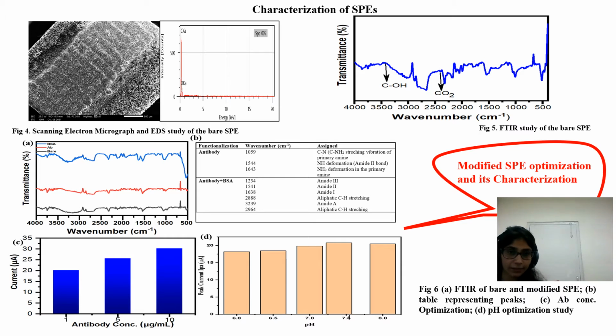Now, the fabricated screen printed electrodes were characterized using scanning electron microscopy, where the micrograph shows the conducting path of the graphite electrode without any break, and EDS spectra show the presence of carbon and oxygen, which confirms that graphite was used for the screen printed electrode fabrication. Further, the studies were also confirmed with the FTIR spectra as shown in figure 5. The peaks represent COH and CO2, which represent the porosity and hygroscopic nature of the graphite.